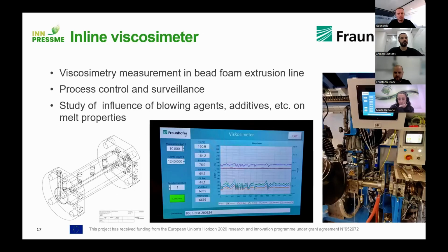Coming to the upgrades that were done during the project. So we developed a viscosimeter, which is now installed on the bead foam extrusion line. It helps us to control and monitor the process, resulting in better quality control of the whole process. And also, of course, we can study the influence of blowing agents and additives on the melt properties. Viscosity is always a big factor, especially when blowing agents are added. You change the viscosity of the melt, and therefore you see really nicely and sensitively if there are changes in the process or in the dosing system.